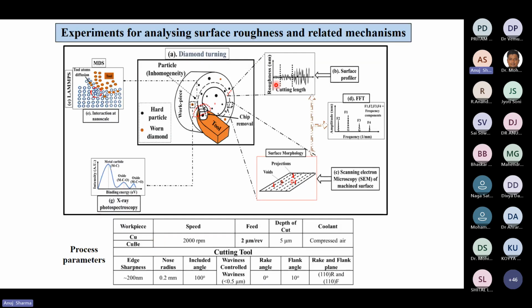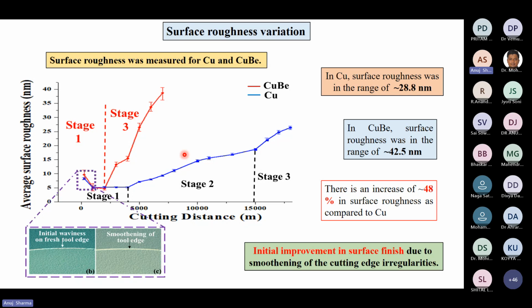So coming to surface roughness, similar cutting parameters were used, and the surface was analyzed for roughness. The morphology was seen on the surface, and any contamination that took place on the surface was also analyzed. First, like the tool wear graph, surface roughness was analyzed. It was seen that similar to tool wear, the surface roughness also increased on both copper and copper beryllium, but the extent of surface roughness was more in copper beryllium. There was almost a 48% increase in surface roughness as compared to copper.